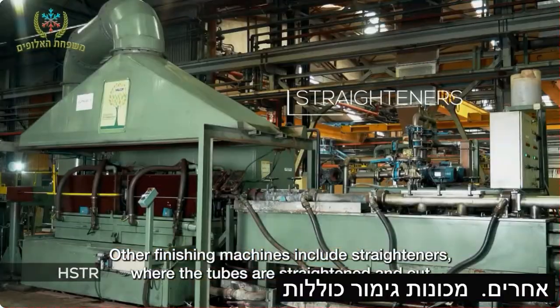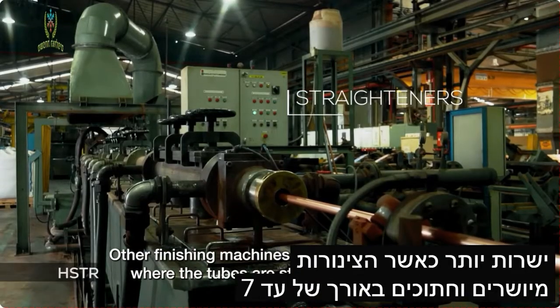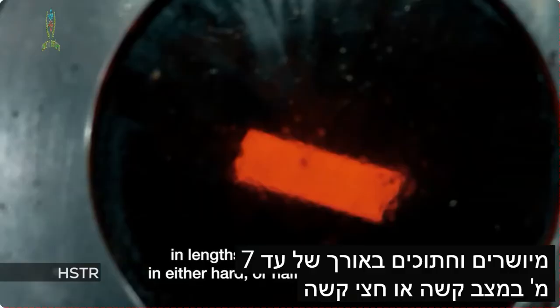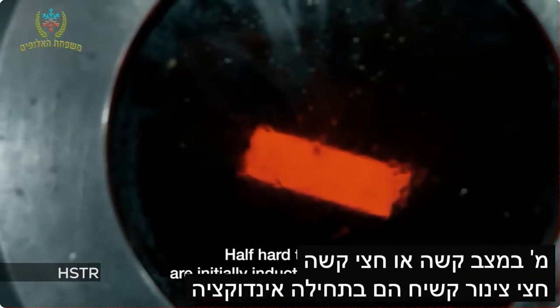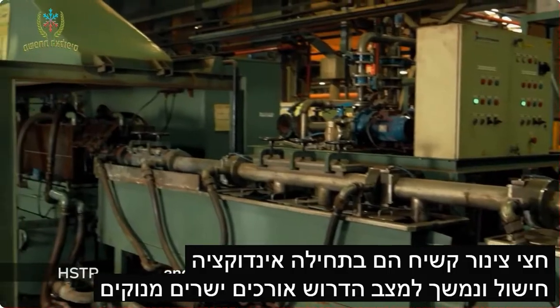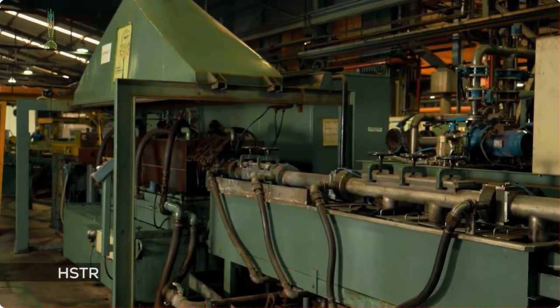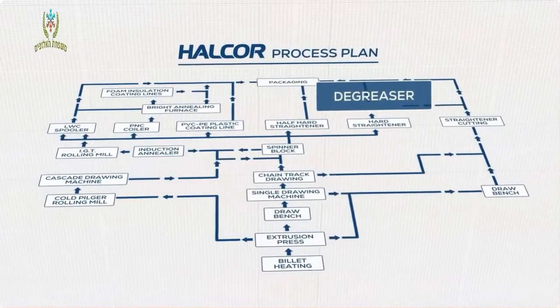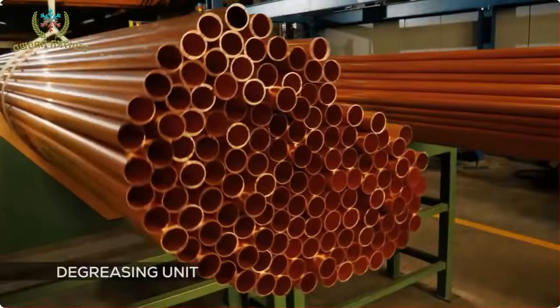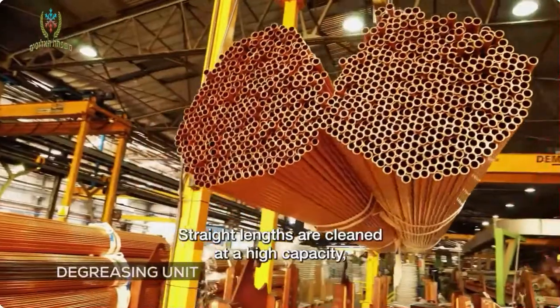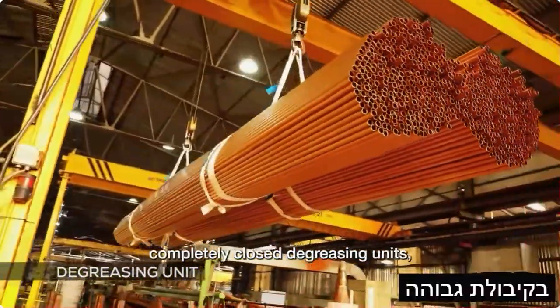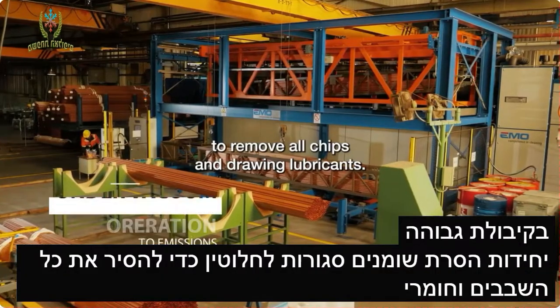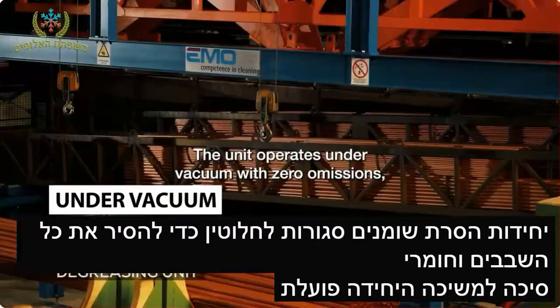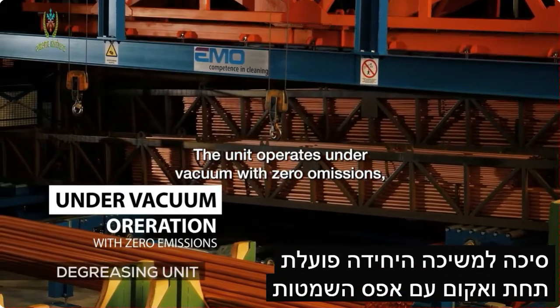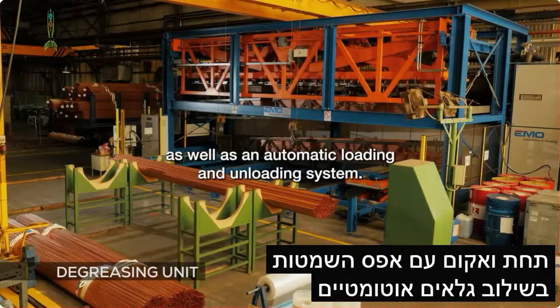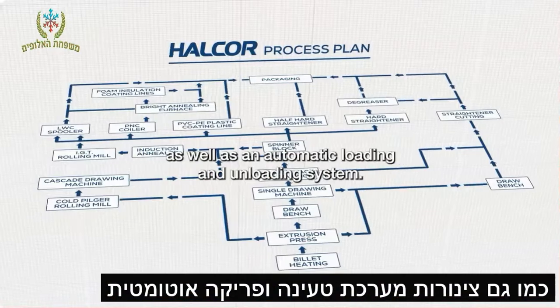Other finishing machines include straighteners, where the tubes are straightened and cut in lengths up to 7 meters, in either hard or half-hard condition. Half-hard tubes are initially induction annealed and drawn to the required state. Straight lengths are cleaned in high capacity, completely closed degreasing units, to remove all chips and drawing lubricants. The unit operates under vacuum with 0 emissions, incorporating automatic detectors, as well as an automatic loading and unloading system.